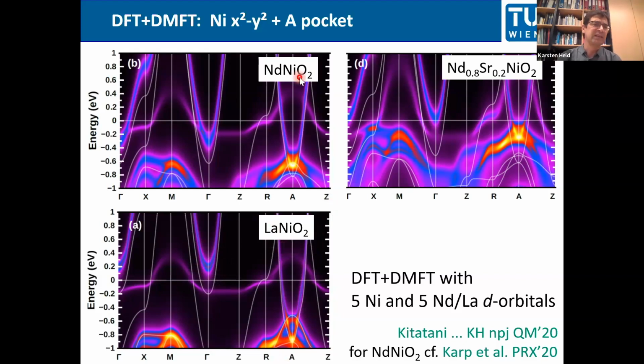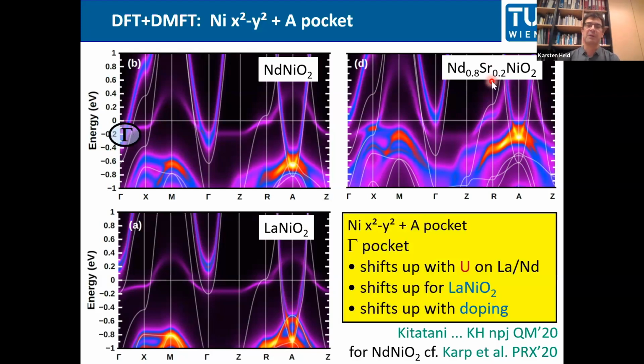Neodymium nickelate is a little bit different. The gamma pocket is still crossing the Fermi level, but if you dope the system, it also shifts up. So here we clearly have a gamma pocket. For the other situations, and that's a superconducting doping, you likely don't have a gamma pocket anymore. And because the gamma pocket is varying so strongly for systems with very similar TCs, we think it is not so important for the physics of the nickelates, but there are other groups that have very different pictures.